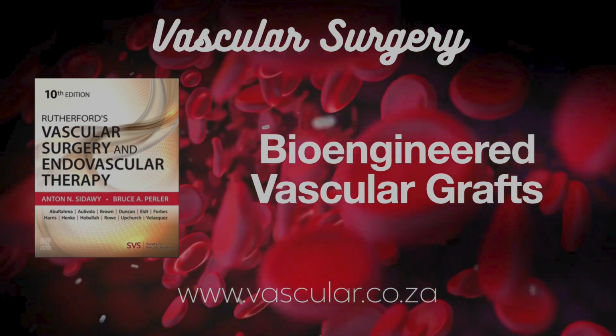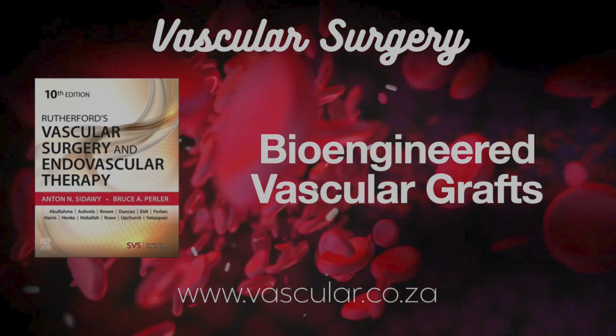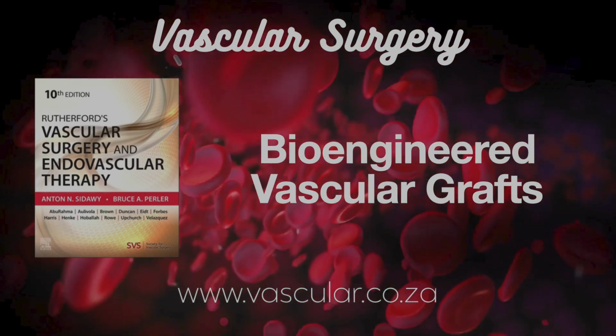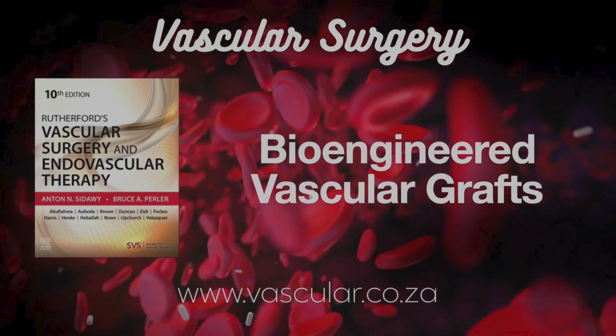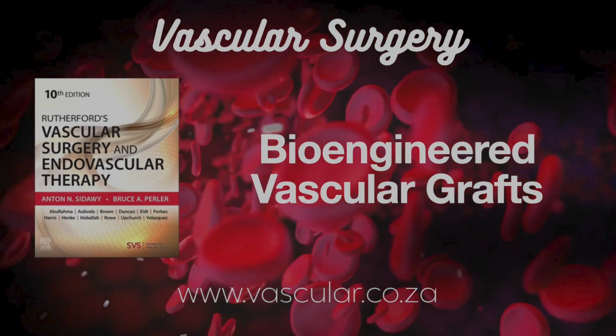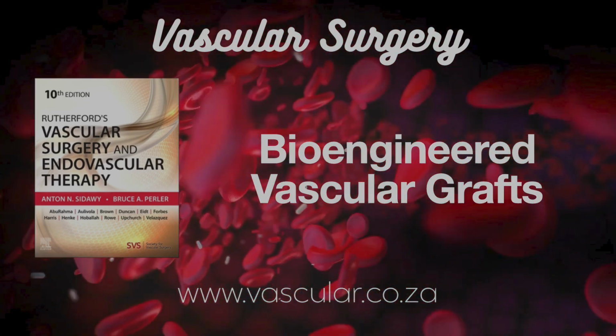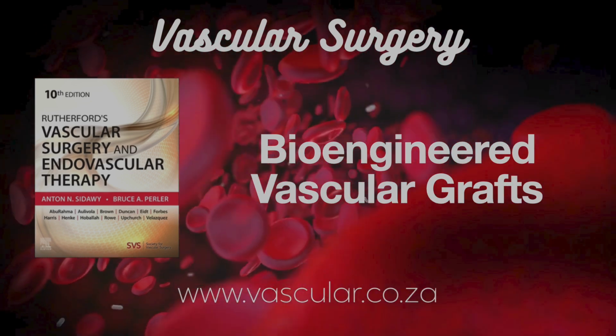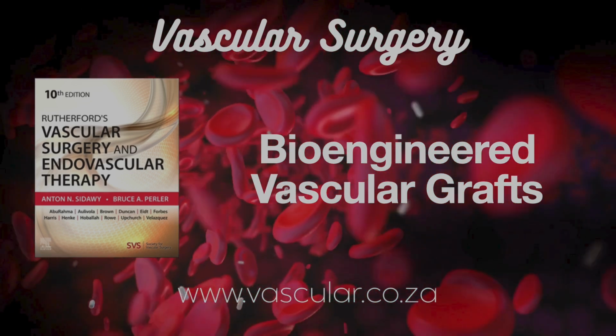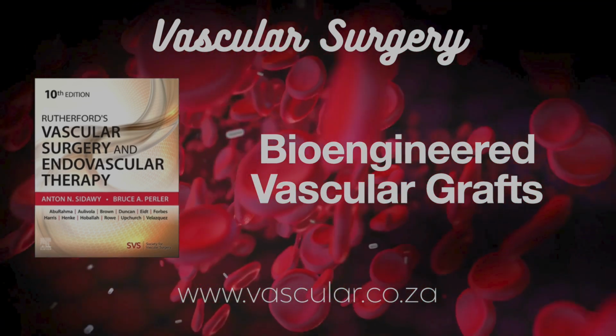Which leaves Humacyte's HAV. That seems to be where a lot of the current buzz is. It really is. The clinical trial data coming out is quite promising. Phase 1 and 2 trials for hemodialysis access, often in patients who can't get a standard AV fistula, showed the HAV was well tolerated. Tolerated meaning? Low complication rates, very low rates of infection, which is huge for dialysis access. And maybe most importantly, biopsies showed that the patient's own cells were migrating into the acellular graft over time. So it was actually becoming living tissue, repopulating.